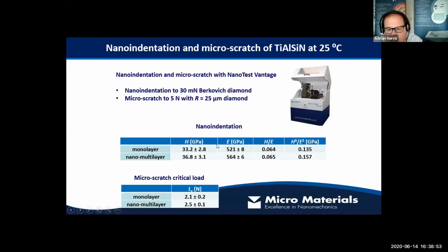So if we look at our scratch data, what we see is a critical load of failure. Critical load for failure with the nano multi-layer coating was higher, so it's 2.5 newtons as opposed to 2.1 newtons for the monolayer coating. So if we were going to predict from our hardness cubed to modulus squared ratio that the multi-layer coating would perform better, it would turn out that was probably a reasonable prediction.